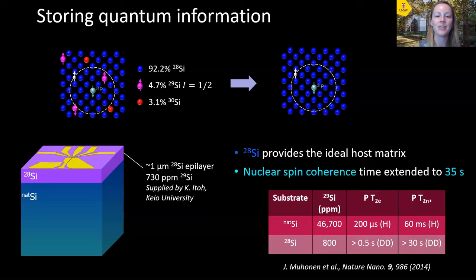And then you switch to silicon 28 and we achieve much, much longer coherence times, all the way up to over 30 seconds for our nuclear spin in silicon 28, which is like a lifetime on the order of donor qubit operations. So we can be sure that we will have high fidelity gate operations because we're not getting decoherence errors introduced before we can actually perform our gate operations.